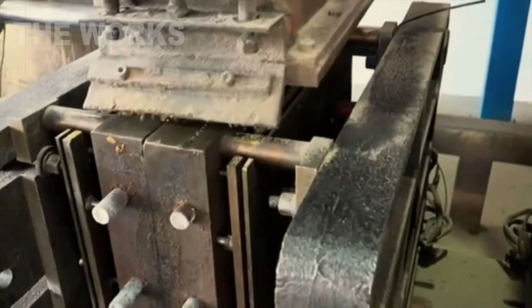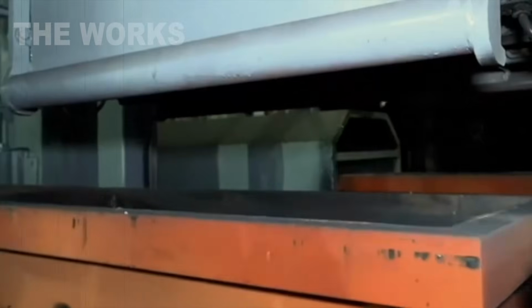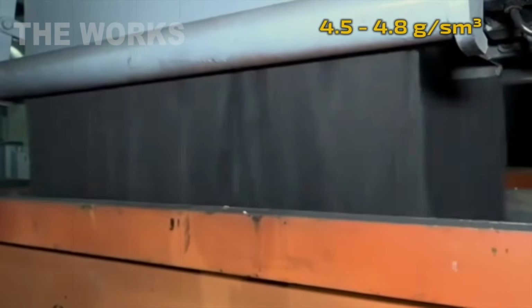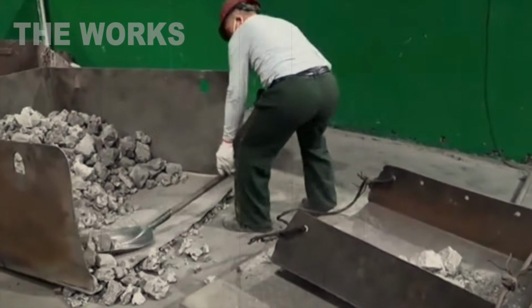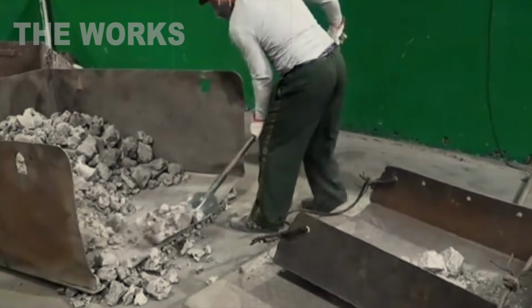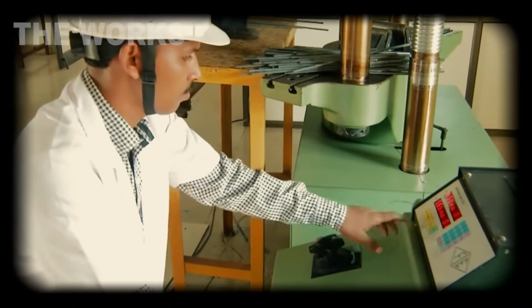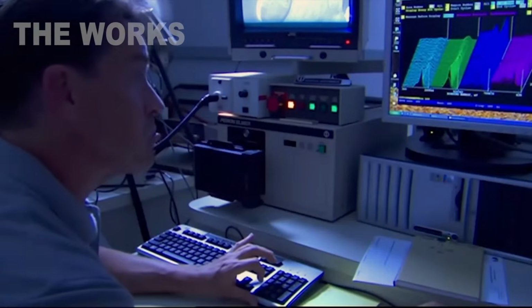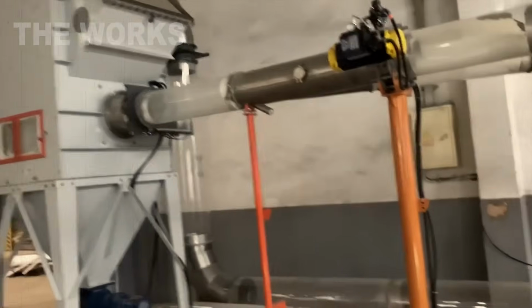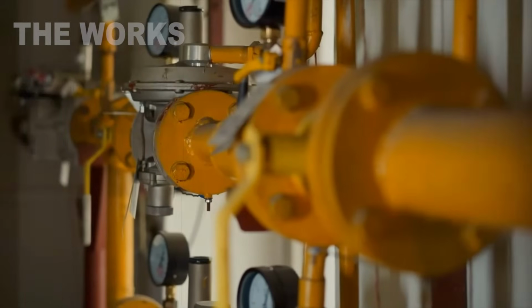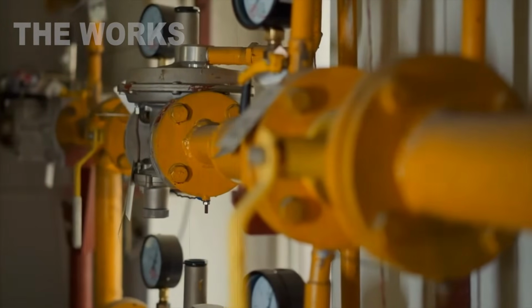The main method for enriching chromite is gravity separation. Chromite is heavier than waste rock. Its density is 4.5 to 4.8 grams per cubic centimeter, while the rock is 2 to 3 grams. The crushed ore is mixed with water, creating a slurry. The slurry passes through jig machines, concentrating tables, spiral classifiers, centrifugal separators. Under the force of gravity, the heavier chromite grains settle faster, while the lighter waste rock is carried away by the water flow.